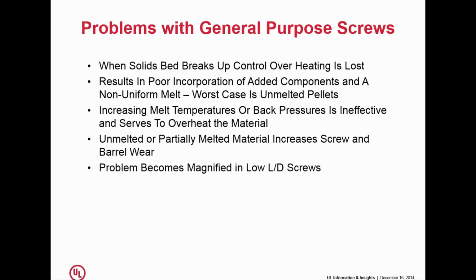And by the way, this problem becomes magnified in lower L over D screws. So if you're running a 20-to-1 screw, you're going to have better success in melting and homogenizing than if you're running a 16-to-1 screw. And if you go back to that table we showed you at the very beginning, remember that one of the other things that happens as your screw diameter gets bigger, because the screw length doesn't change, is that your L over D is going down as your screw diameter gets larger. So that's another thing that's happening when you buy the bigger barrel that is going to handcuff you in terms of getting a good process.